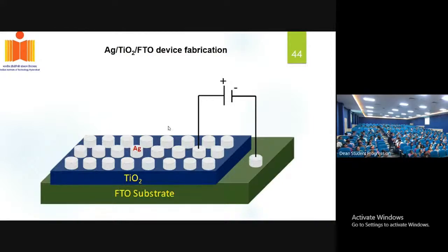Once we confirm the material characteristics, which is the most important part for developing any device, we make the device. We have taken FTO, the fluorine doped tin oxide substrate, and on that we deposit the titanium dioxide thin film. Then we put the top contact, silver, as the top electrode. As you can see here, we applied the potential difference between the top electrode and the bottom electrode. So I can call it a CPP structure, current perpendicular to the plane structure.